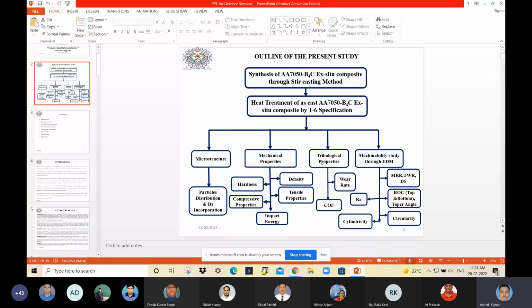I'll just give an outline of what I have done in my PhD. Basically, I developed one composite material based on the aluminum alloy 7050 series mixed with B4C, an ex-situ composite. There is a basic difference between ex-situ and in-situ. In-situ, we have an alloying kind of thing: we melt it and form the reinforcement inside that melt. Ex-situ means we are adding it from outside and trying to make a bond with the matrix material. This ex-situ composite was developed through a stir casting method. After developing the composite, we gave it a heat treatment as per the T6 specification prescribed for aluminum alloy 7050.